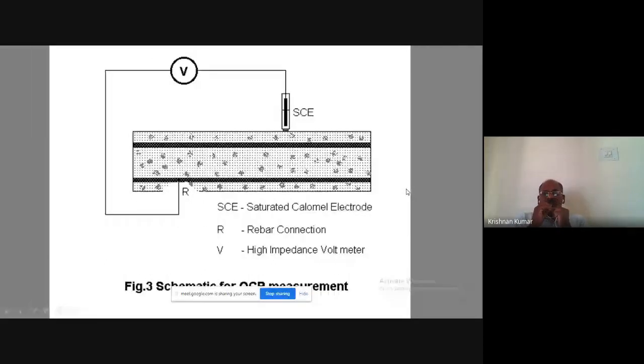Now, the corrosion has happened. We must understand the extent of the corrosion and where it is happening. We do not know where, because the cover concrete and plaster are there, so we have to use a non-destructive testing method. Universally, people use open circuit potential measurements with a reference electrode. This is also called half-cell measurement.